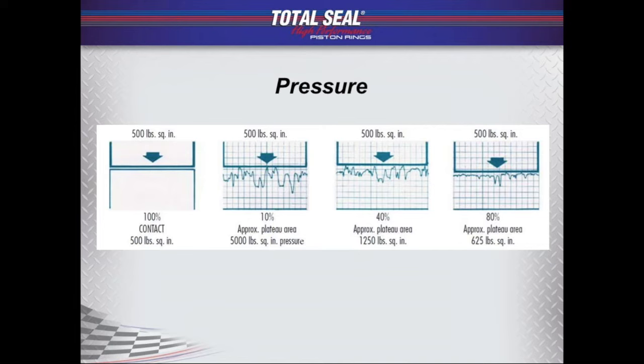And the power numbers are coming up, the oil consumption's going down, blow-by numbers are coming down. It's because we're creating that plateau, but the ring's doing the job. If we've got a really well plateaued cylinder, it's going to come in almost immediately. You're going to have that engine on the dyno, it's going to go one, two, maybe three hits. You're going to have that great ring seal, fantastic blow-by numbers, dry as a bone. That tells you right there, you've got a really, really good cylinder finish.